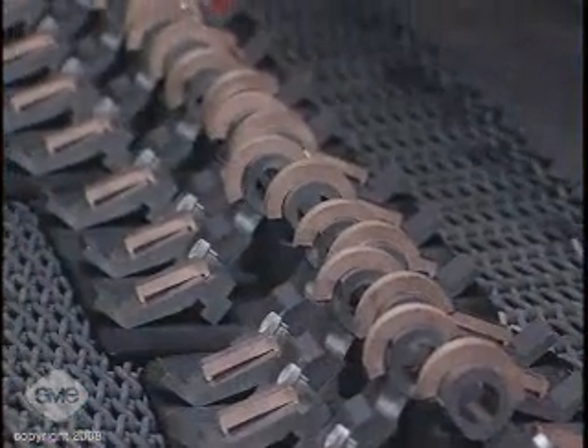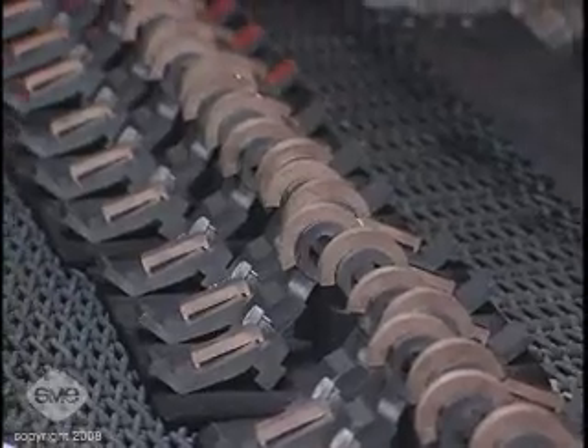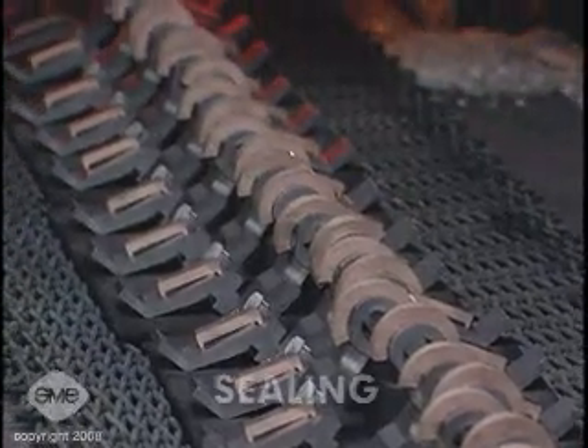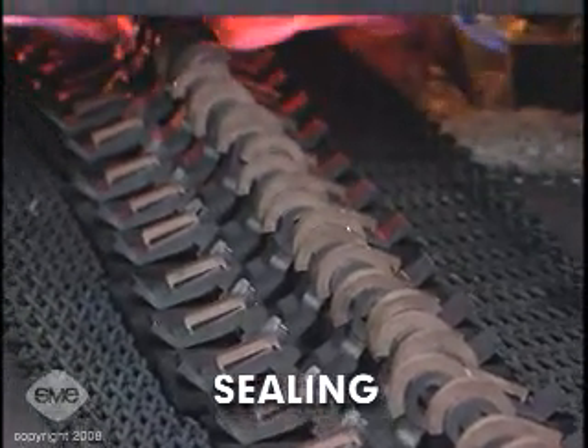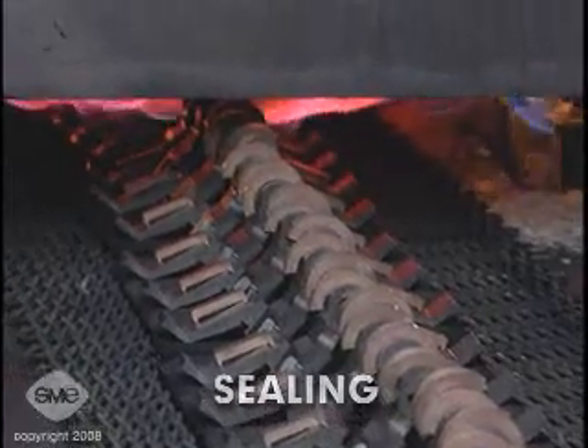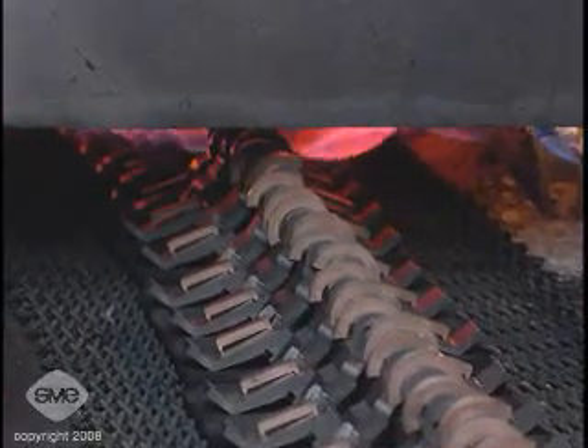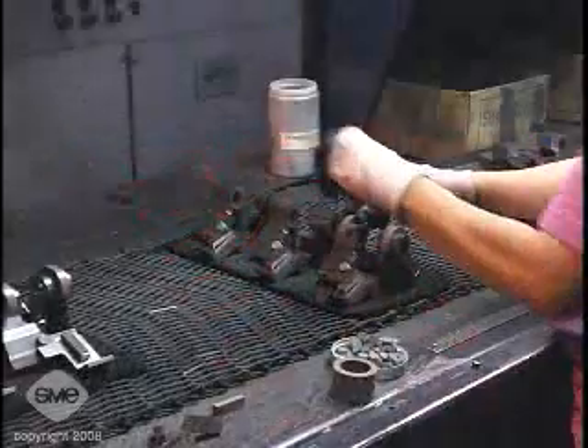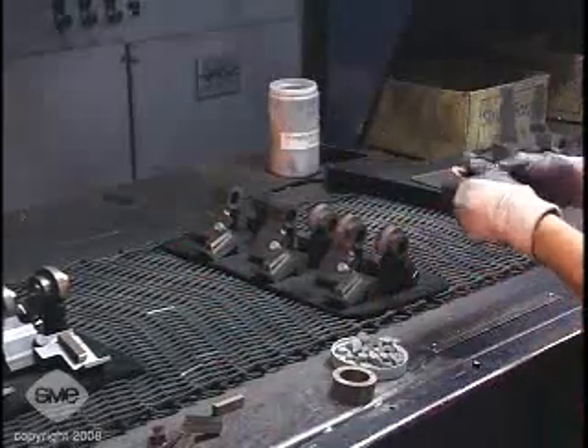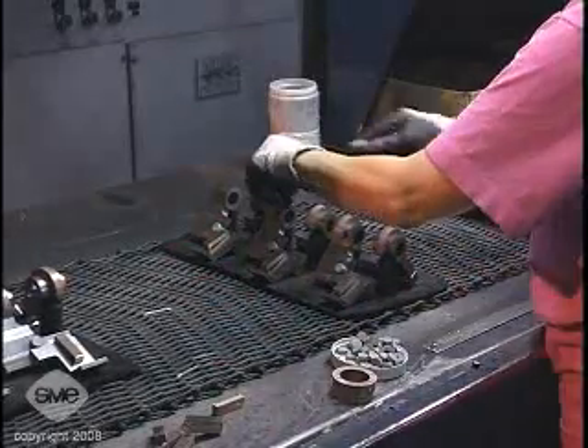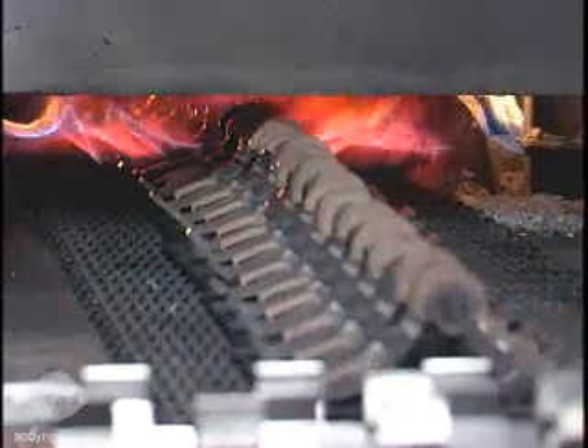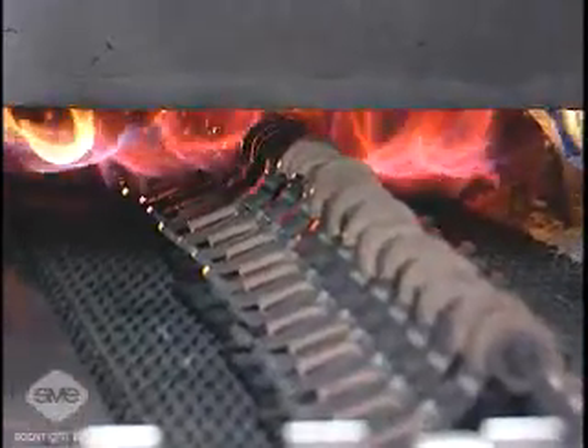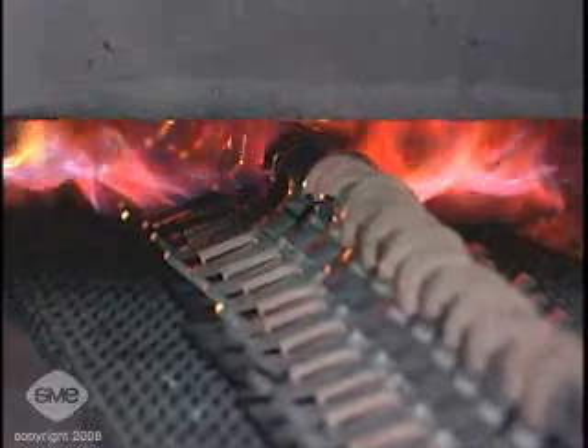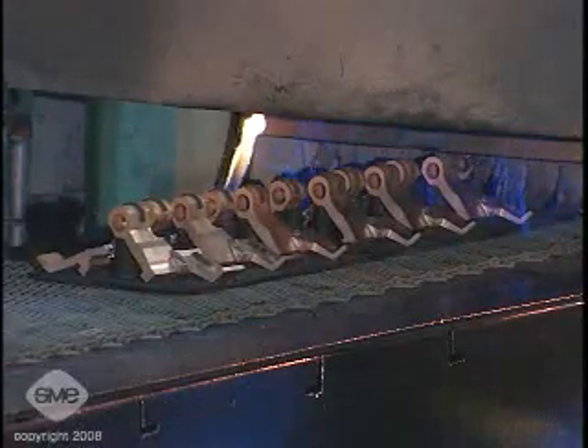Part porosity can be eliminated or substantially reduced by impregnating or sealing a part with a polymer resin or a metal having a lower melting point than that of the part base metal. Copper is commonly used for iron parts. Copper slugs are placed on the parts and passed back through the sintering furnace. The copper melts and infiltrates the pores and, on cooling, solidifies.